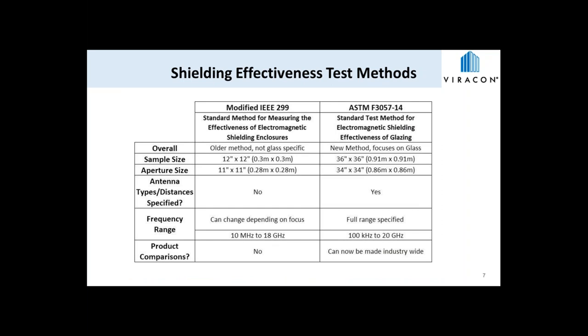So there's two different test methods to calculate shielding effectiveness, the IEEE 299 and the ASTM F3057. The IEEE standard has been around for a few decades and is kind of a catch-all method for any material. As a result, it's been modified for glass testing purposes, really picking out certain portions of the procedure, but leaving out others. Because of this, the new ASTM test procedure was developed. This test focuses on the glass itself by making the frame system one of the control variables. The ASTM method also increases the sample and aperture size, really trying to force the signal through the glass and not through the frame.